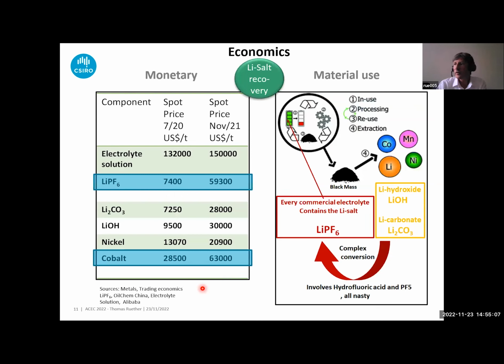So the value proposition of our lithium salt recovery technology has a monetary and material use aspect. In the material use aspect, we are looking at how high value lithium battery components like cobalt, nickel, and lithium can be recovered in a common existing process. Here, lithium is extracted typically as lithium hydroxide or as lithium carbonate, and these then have to be further processed in a complex conversion process to make the LiPF6, which is the common lithium salt in every existing commercially used lithium-ion battery.